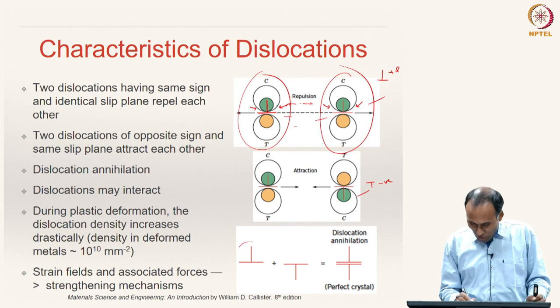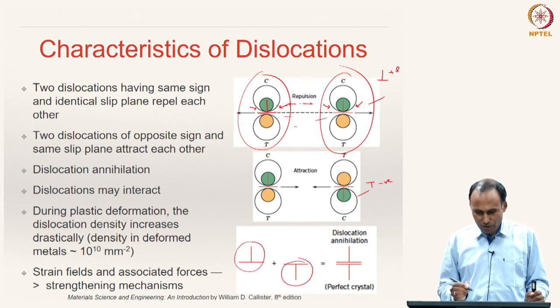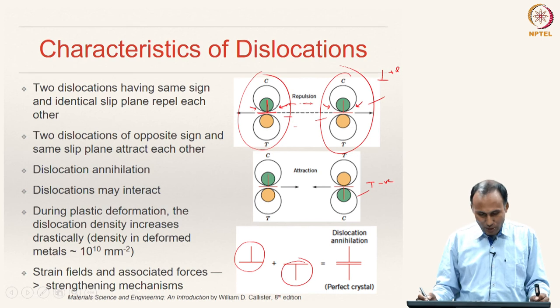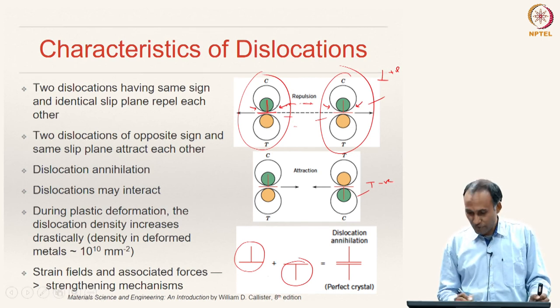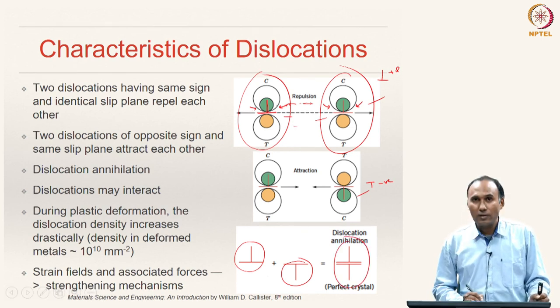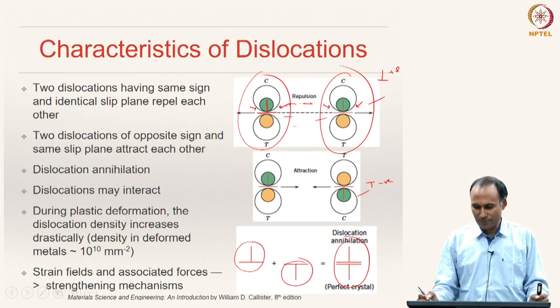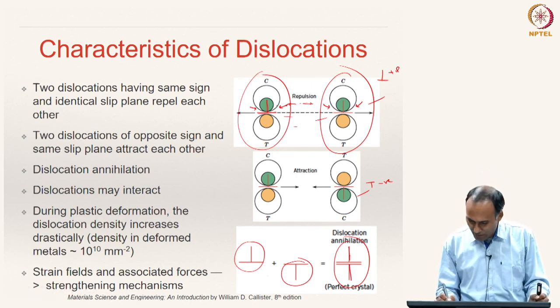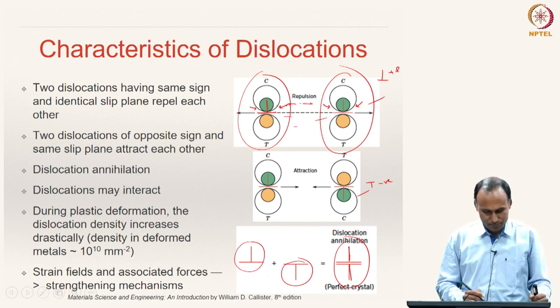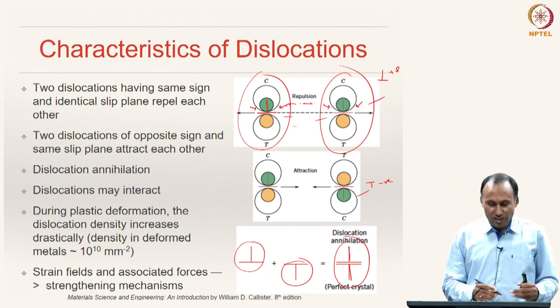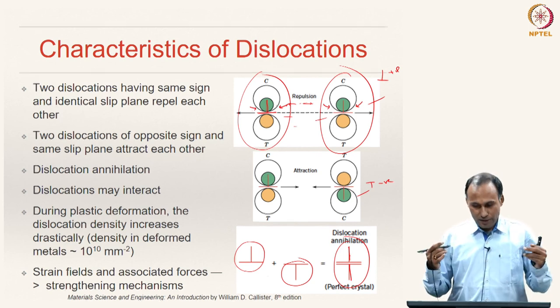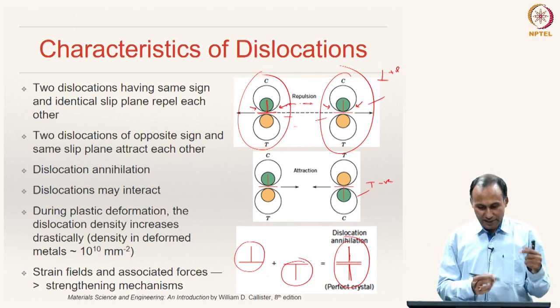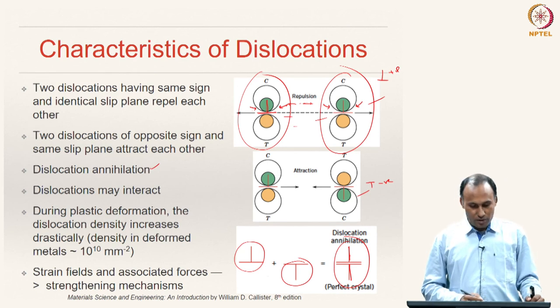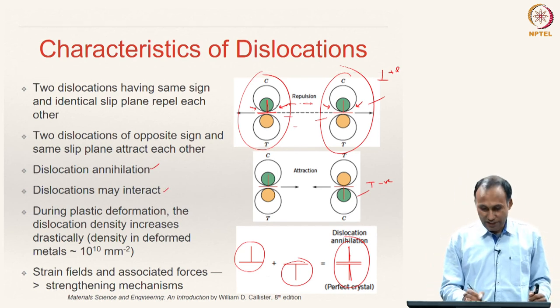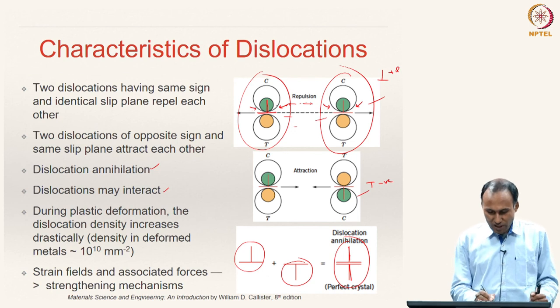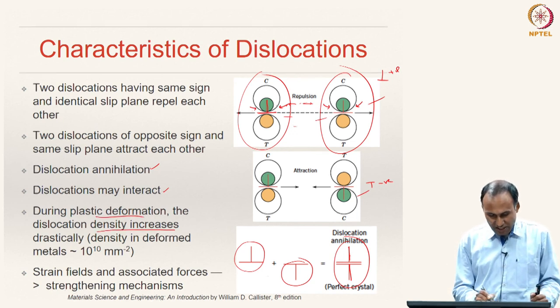However, if two dislocations are of opposite sign and again in the same slip plane are coming together, they attract each other in order to annihilate. They annihilate and become a perfect crystal, right? Because you have an extra half plane here, and these two become a perfect crystal. So the dislocations can either repel each other or attract each other, and by attracting, they annihilate. So the dislocations can interact, and during plastic deformation, the dislocation density increases